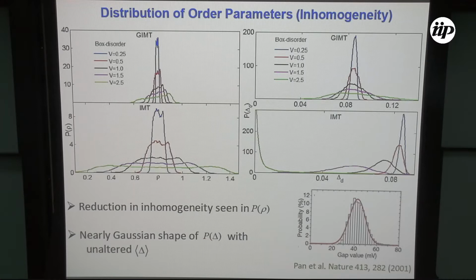Now, if we want to understand what happens to the inhomogeneities themselves, in our problem we have two primary order parameters: the density or local doping, and the superconducting order parameter. If you look at the distribution, as I told you, we have taken a box distribution for the disorder, so we expect the density to behave similarly. In IMT, we will have more or less a box distribution, and if you increase the width, this also increases. But you can see in the same scale, if you include strong correlation, it shrinks. So the inhomogeneity in density gets reduced significantly.